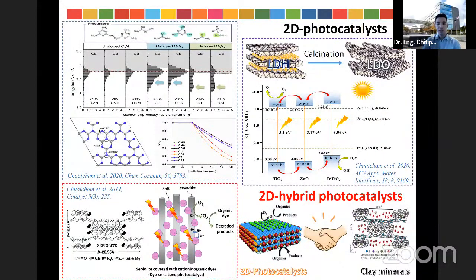So this slide shows some of our achievements about two-dimensional materials and clay-based photocatalyst composite. For example, we prepared oxygen or sulfur-doped graphite carbon nitride, which is a two-dimensional material. And also we prepared the titanium layer double hydroxide and layer double oxide by heat treatment of the layer double hydroxide. And we use this material for the phenol degradation.